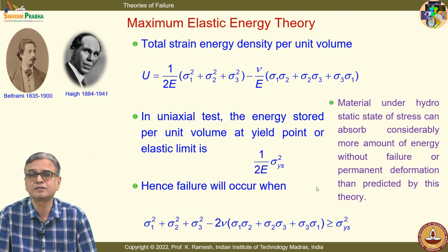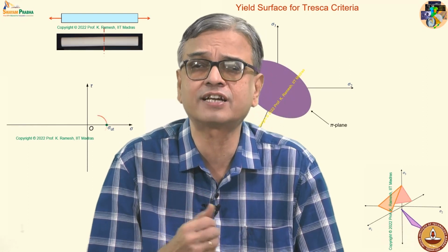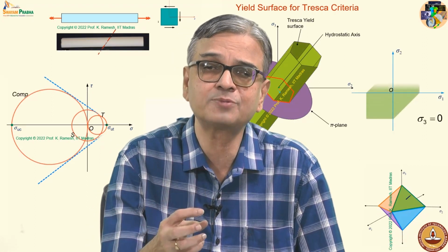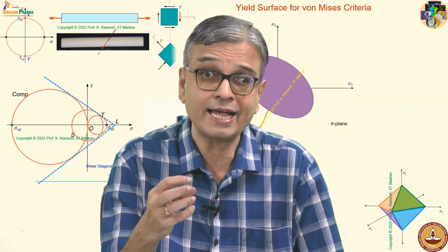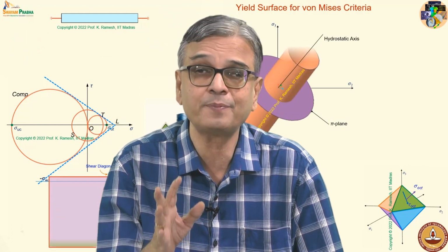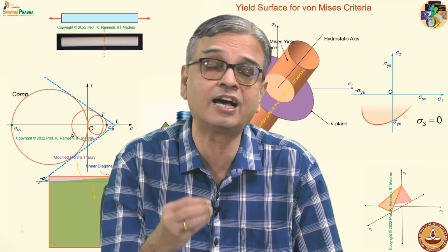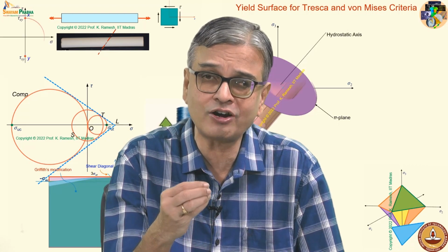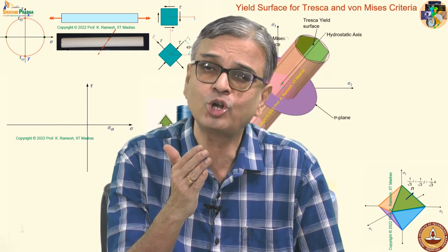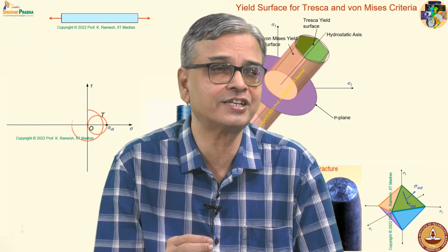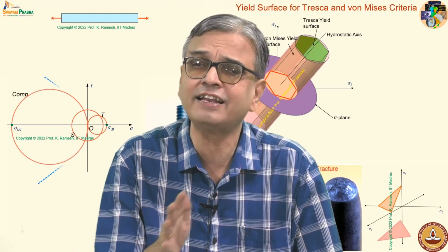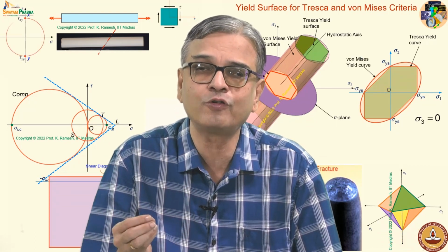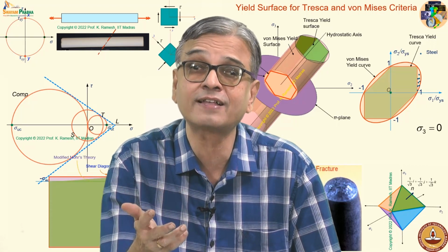See, people have observed materials can withstand very high levels of hydrostatic stress. Nothing happens to them. Even if you take a brittle material like glass, you take a glass bulb and immerse it in a liquid. If you do a careful experiment, see, experiments have to be done carefully. What people have found is it is able to withstand very large pressures. Nothing happens to it. And when you release the pressure, if you are not careful, failures people have observed. We have also made an idealization that we have an elastic continuum. In reality, nothing is an elastic continuum. You have micro cracks. What people have found is if there are micro cracks and if fluid gets into those micro cracks, then failure has happened much earlier.